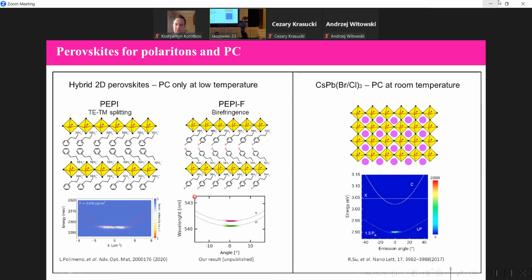But these are results at cryogenic temperature again. If you want condensation of polaritons in perovskites at room temperature, we need fully inorganic perovskite like cesium lead bromide or chloride, like in this picture - this is a three-dimensional perovskite without any layers.